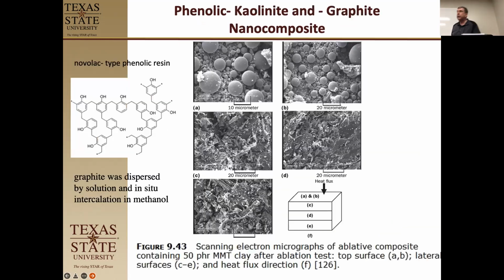Okay, so let's shift gears again. All right, this is different. This is a phenolic with a kaolin. Kaolinite and montmorillonite are charged clays, aluminosilicates. Kaolin is low, it doesn't have so much charge on it, and so it's kind of easier to disperse. And again, we're using a phenolic resin, and this is a Novolac type phenolic resin. They basically just have a catalyst with formaldehyde and phenol. It makes the cross-linked matrix here.